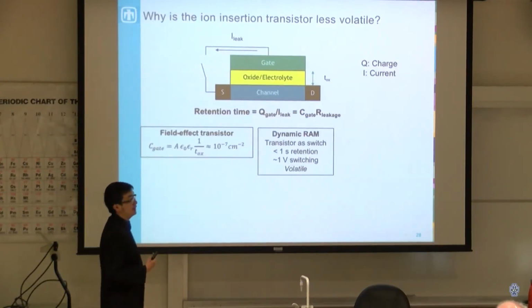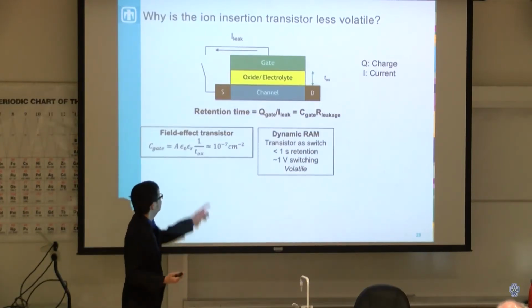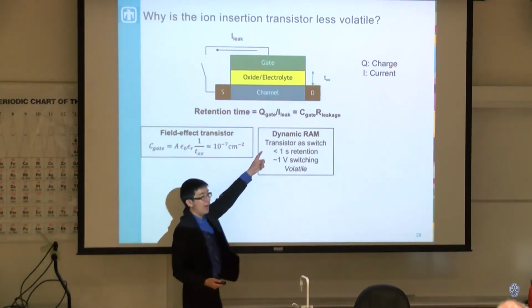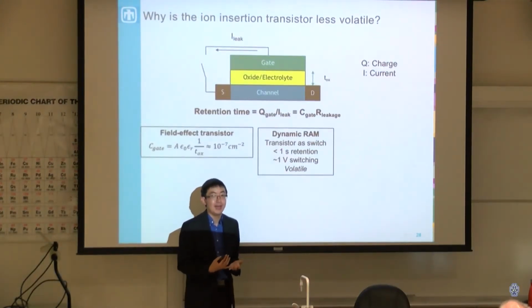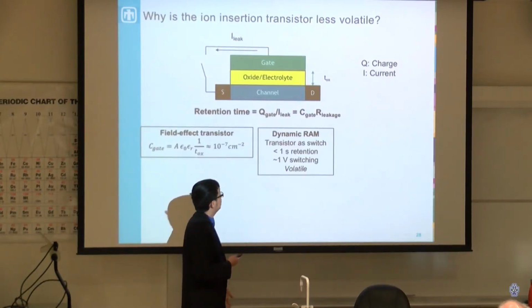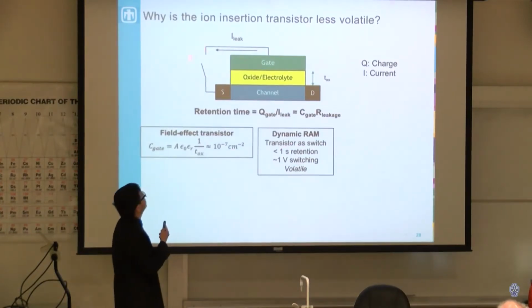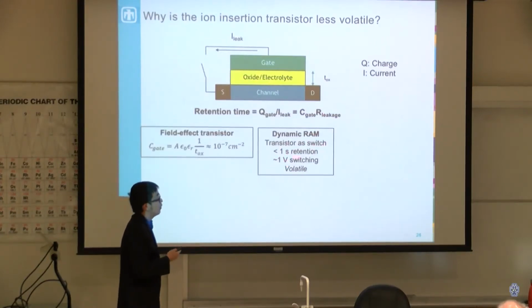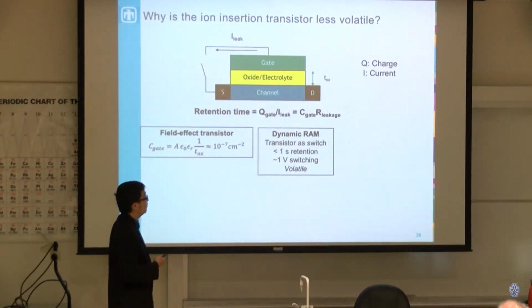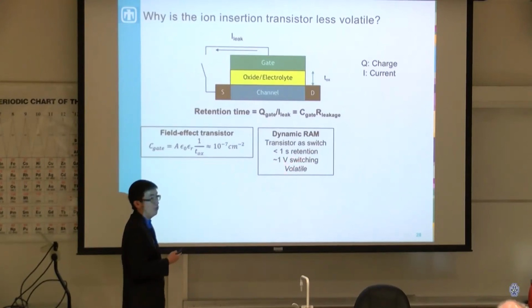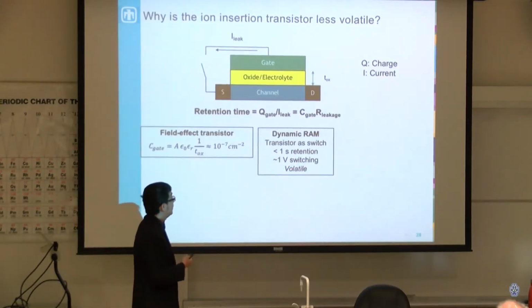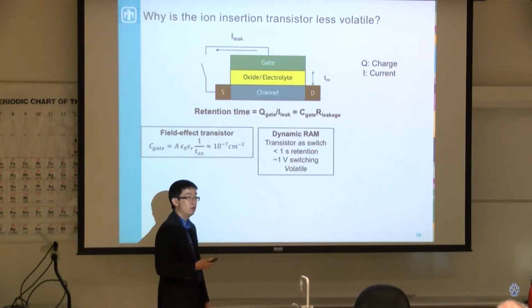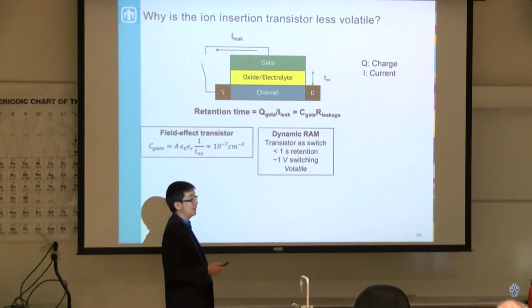So if you want to operate this in a volatile mode, so this isn't a lot of capacitance, we can have these memory elements called dynamic random access memory, which in this case we use another transistor here basically as a switch, and we can retain that for about 1 second of retention time. But the advantage here is that you only need about 1 volt to program this device, and so you get a low voltage but volatile mechanism.